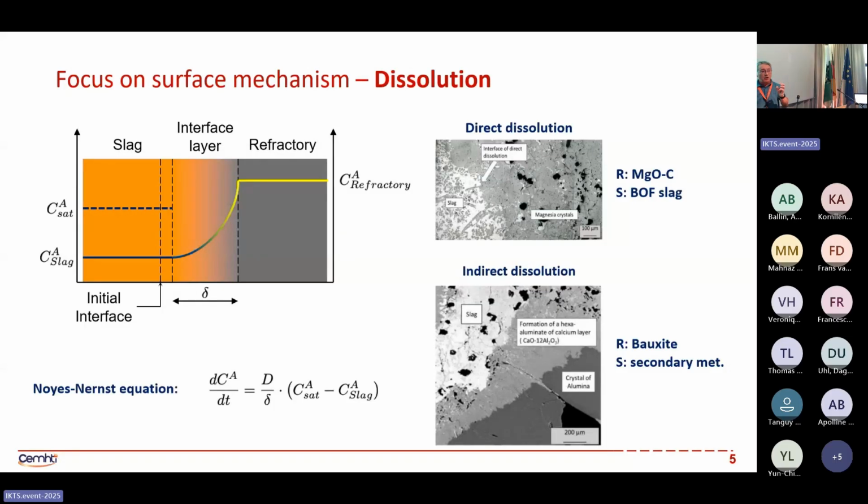That means that there are some atoms, for instance aluminum, calcium, and oxygen, to take the example of a CaO-Al2O3 slag. What is inside? It is a liquid, but the atoms cannot do what they want. They have strong relations between themselves due to the local organization of calcium, aluminum, and oxygen. The aluminum has 4 or 5 oxygens around it, creating a tetrahedron. And sometimes they share an oxygen, a bridging oxygen, with another tetrahedron, etc., and you have a polymeric chain.